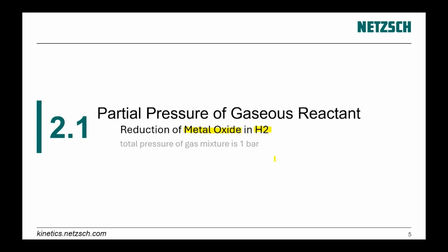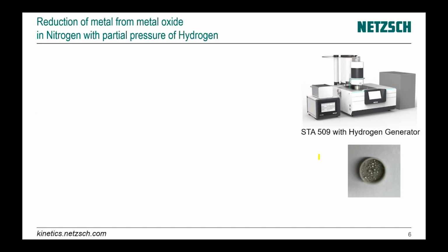Let's make kinetics for the measurements where we have several measurements with a gas mixture. The total pressure is 1 bar, and the gas mixture has two components. One of them is an inert component, nitrogen, and the other one is the reactive component, hydrogen. The measurements are done on our new STA 509 with hydrogen generator. After the measurement of metal oxide, for example tin oxide, we have pure tin, and it produces a very nice melting peak for the second heating.